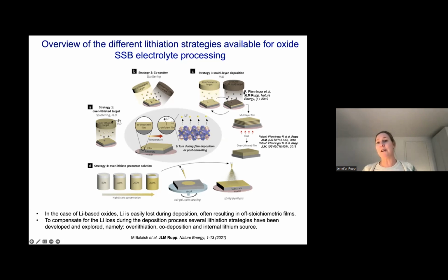So you have to think much more about lithium loss in a smart way. And so here's an idea that we came up with. We could make the lithium garnet pellet, and you can over-lithiate it only to a certain extent so that it remains dense in sintering.